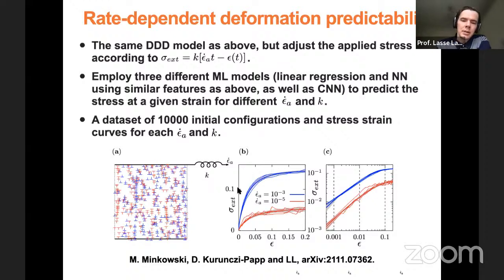So here, of course, you have some rate effects also in the deformation process, just to mention briefly, which means basically that if you impose a very small strain rate, then your stress at a given strain tends to be smaller than it is if you impose a large strain rate. So this blue curve has two orders of magnitude larger strain rate than the red ones. Then you also have some sample-to-sample fluctuations here, which is actually what you're trying to predict.